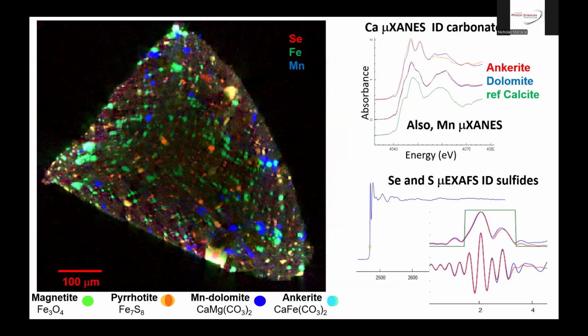And as for the identifications, some examples for the carbonates that are present there, we use calcium XANES. So you see on the bottom curve, that's a reference of calcite, simple calcium carbonate, and its structure is two peaks. Dolomite, which is a calcium magnesium carbonate, each of those two peaks is slightly split. And ankerite, which is a calcium iron carbonate, same structure for all three, but just different chemistry. In ankerite, those peaks are even more widely split. So the XANES is quite sensitive to the local chemistry and can be used to identify different minerals in different locations in the sample.